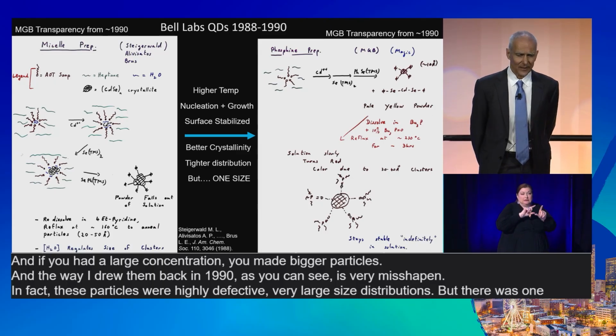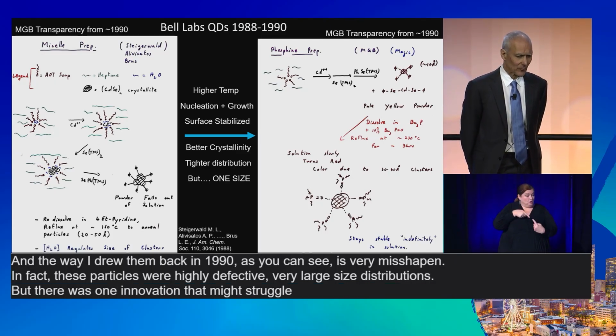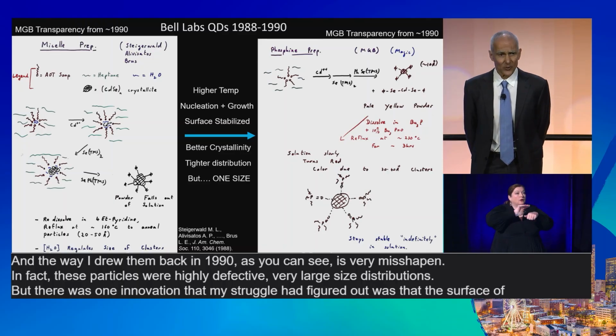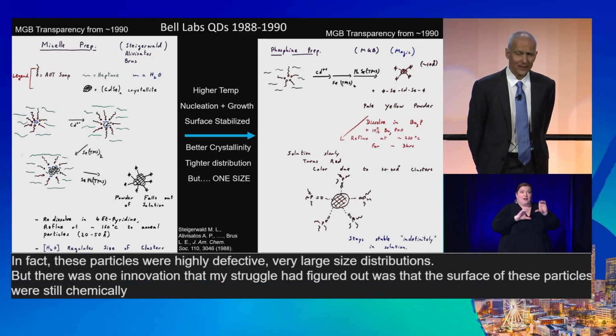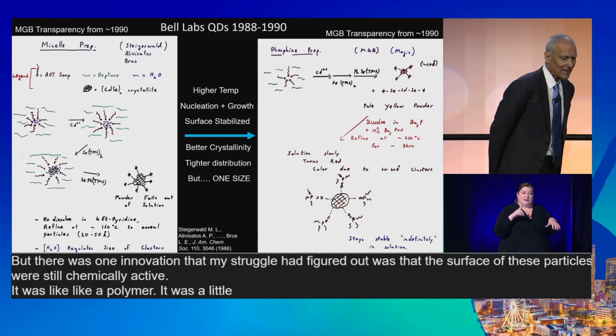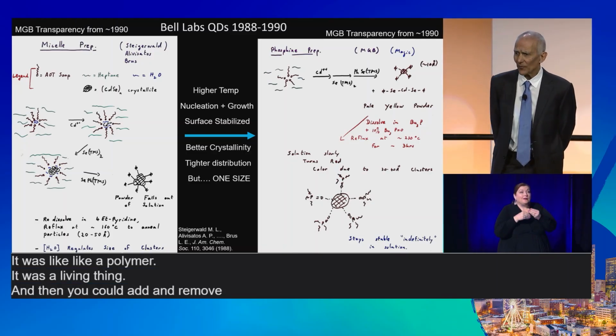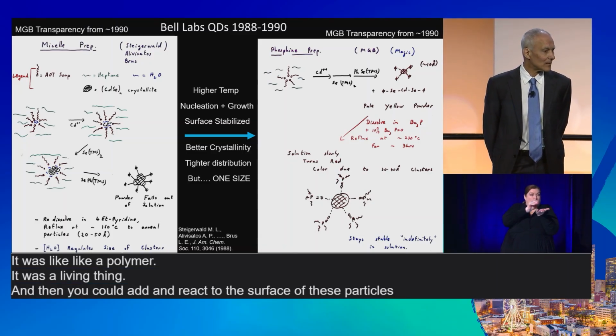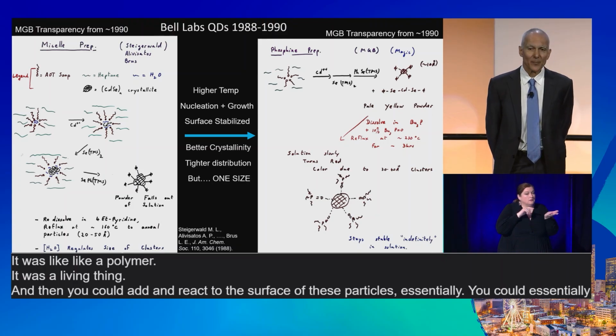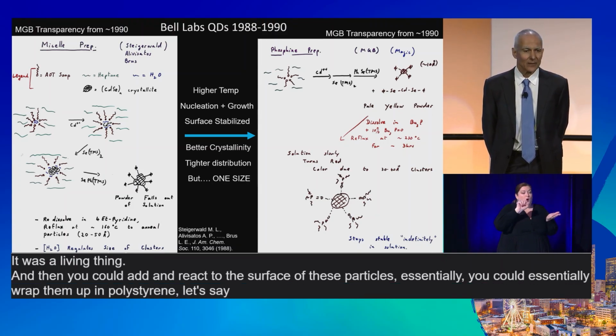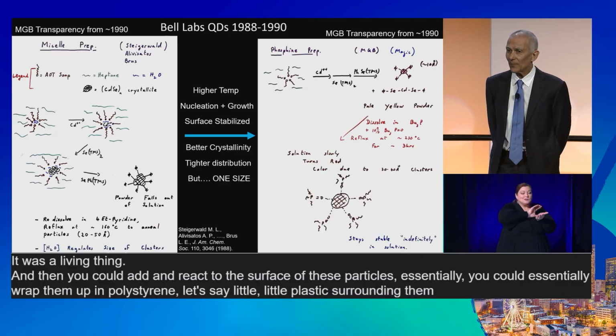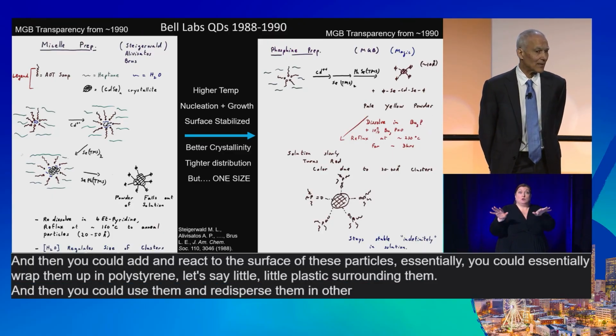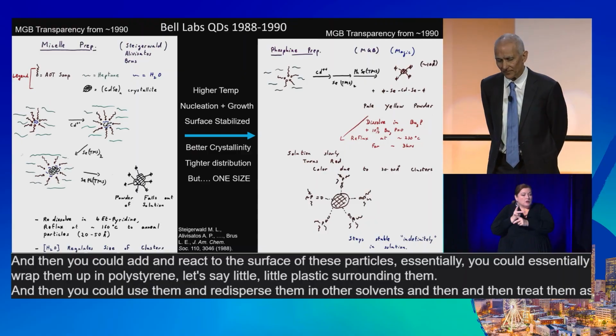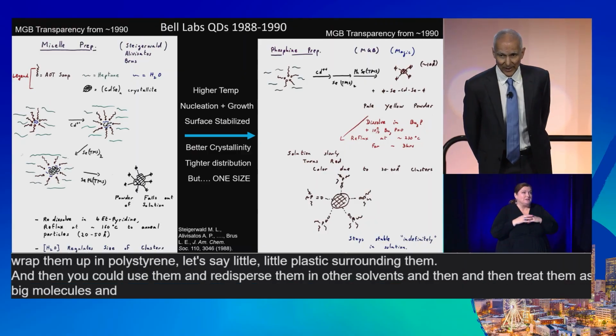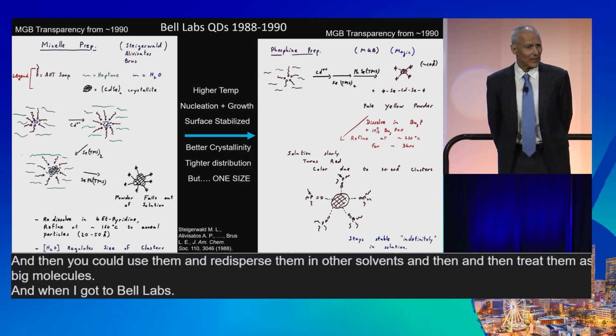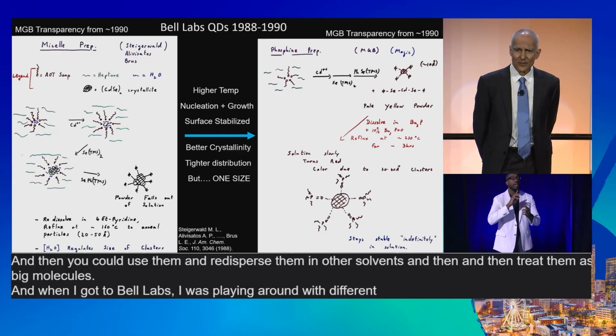But there was one innovation that Mike Steigerwald had figured out, that the surface of these particles was still chemically active. It was like a polymer, it was a living thing. And then you could add and react to the surface of these particles, essentially wrap them up in polystyrene, let's say. Little plastic surrounding them, and then you could redisperse them in other solvents and treat them as big molecules.